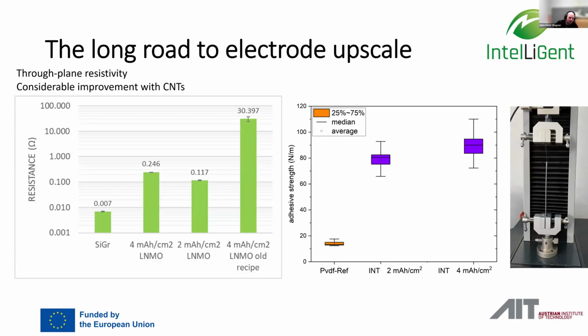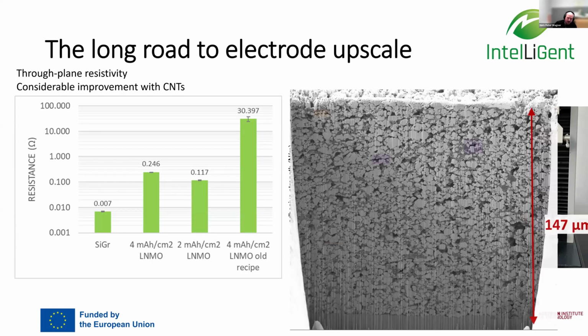We worked quite a lot on the chemistry and on the processing, and we were able to achieve LNMO cathodes that have through-plane resistances that are not far off the regular 2 milliampere hours per square centimeter in our final generation. And also the adhesive strength of our electrodes is much better than with a PVDF reference. This is an example measured at our colleagues from AIT.